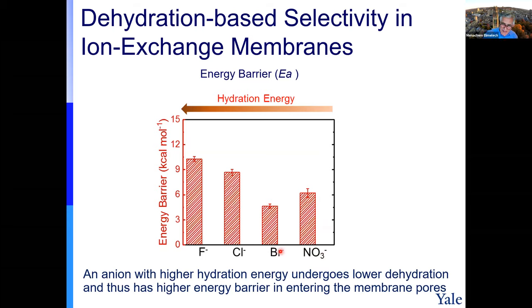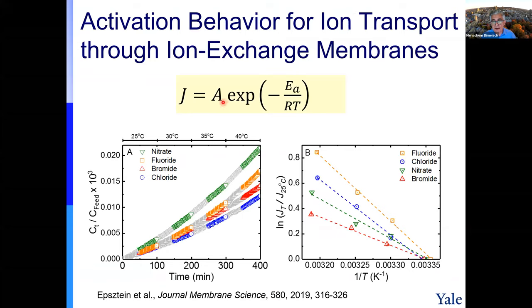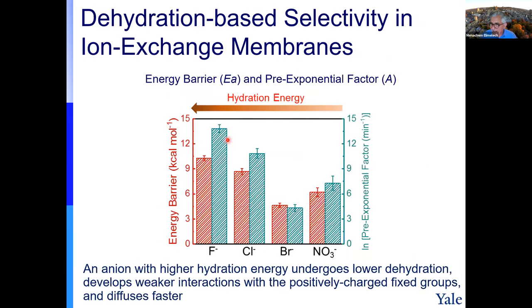So we see that this energy barrier correlates to the hydration energy. We also measured this pre-exponential factor. This pre-exponential factor can tell you what the flux would be if, in principle, there were no energy barrier, so zero. And we see the same trend. The reason, again, is this interaction. Fluoride has the highest hydration energy, so it doesn't dehydrate well. And because it doesn't dehydrate well, it doesn't interact well with the functional groups on the anion exchange membrane, the positively charged group. And this is the reason why it moves faster.